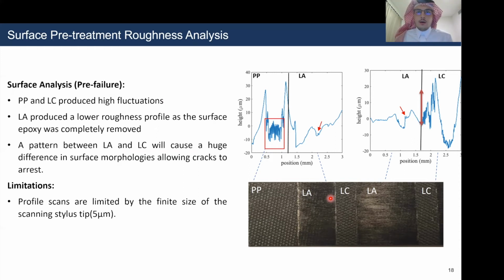And what we noticed out of the results was that the peel ply and the LC produced high fluctuations on the surface profile. And these are indicators of contaminants on the surface of the peel ply and the laser cleaning. While the LA produced a low surface profile with not many fluctuations as compared to the LC. And this is mainly due to the full exposure of the fibers and the removal of epoxy off the surface.